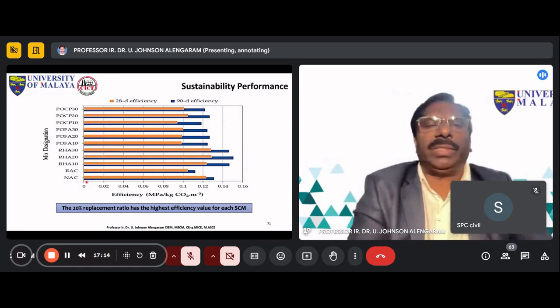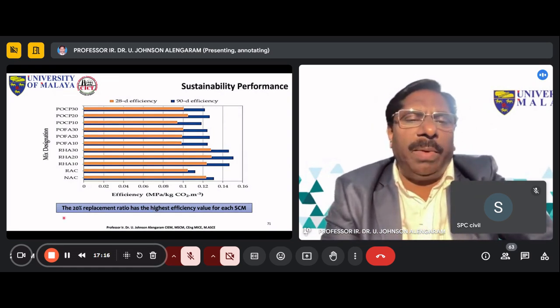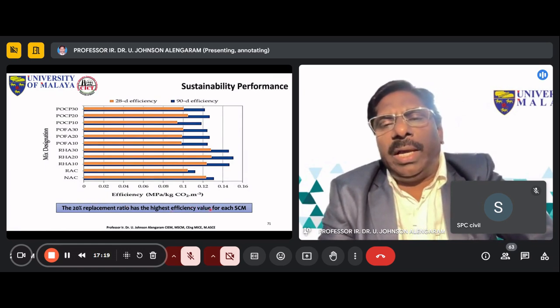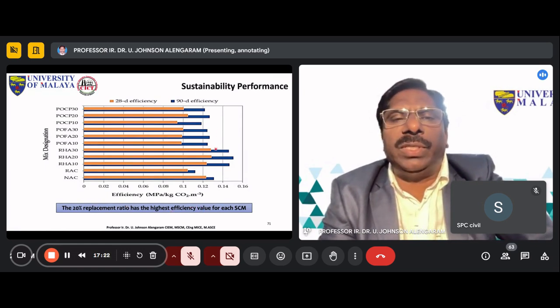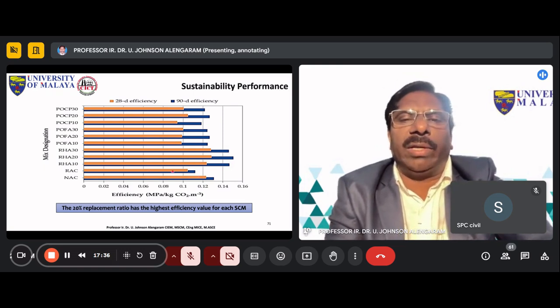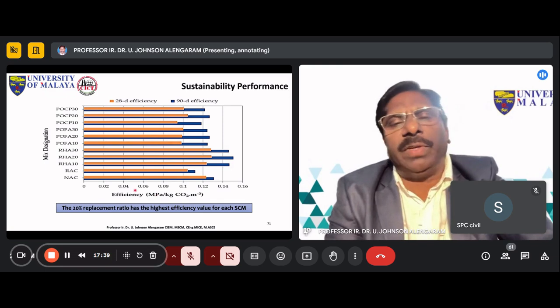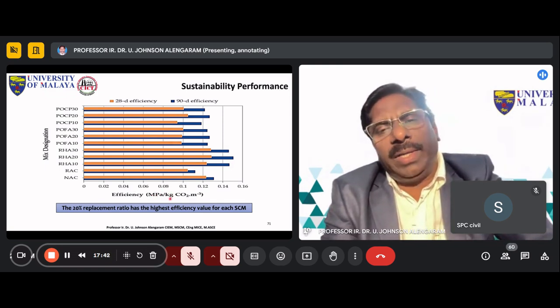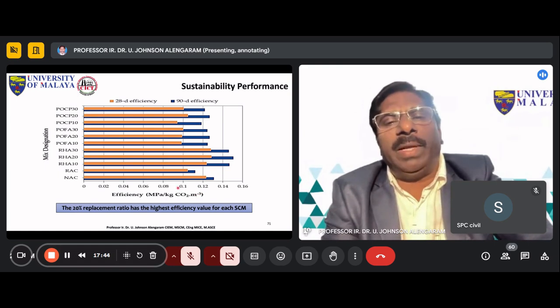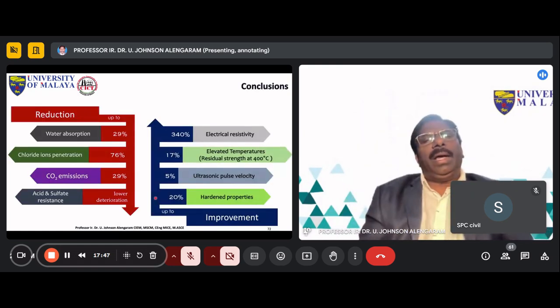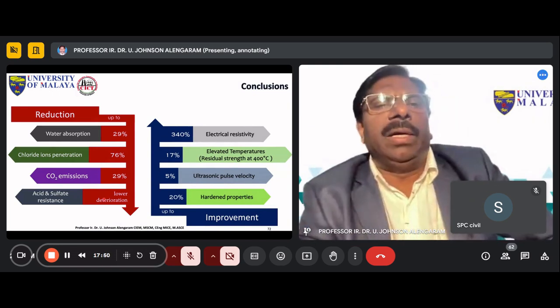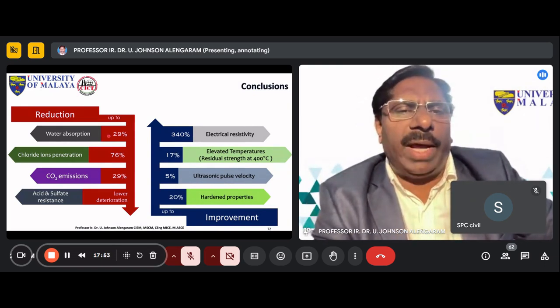And for sustainability performance, we got the 20% replacement ratio as the highest efficiency. If you see this is 20% rice husk ash, compared at 28-day or 90-day efficiency against the normal concrete, you see they perform better than this recycled aggregate concrete here. And this efficiency was measured in terms of strength per kg of CO2 emission per cubic meter. So you can see this. Okay, and a summary of this is to check the reduction: the water absorption was 29% lower.